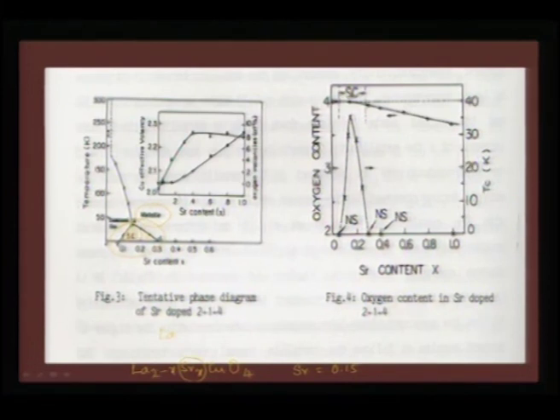If it is below 0.15, then it is in a semiconducting-like state. So, this is critical for us to understand the compositional limit, because as the strontium content increases, you can see that it is fully oxygenated, and therefore the oxygen vacancies are at their maximum somewhere around this region, and this is critical for high Tc. You would also find somewhere around this the nominal copper valence state is around 2.1 to 2.2, which means copper is having both copper 2 plus and some amount partially substituted with copper 3 plus, and that is coming because of oxygen deficiency to bring about the right charge neutrality.